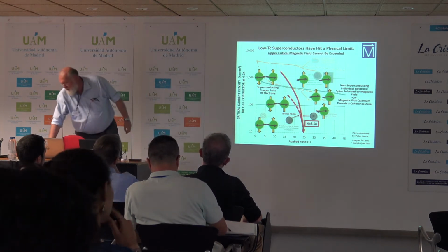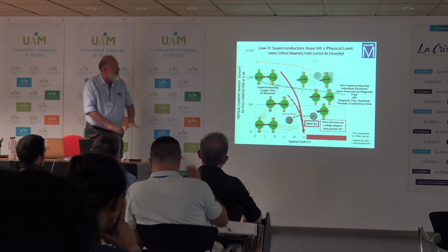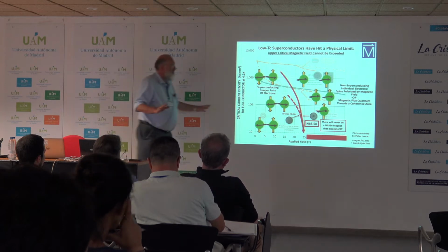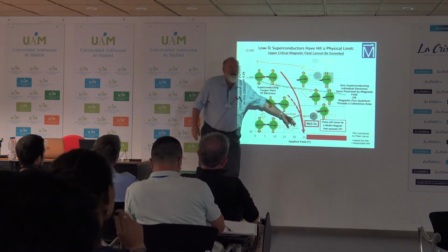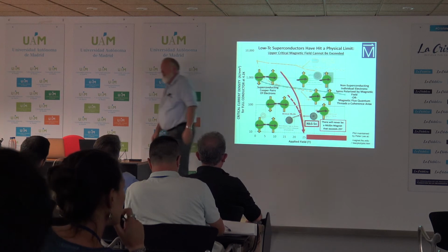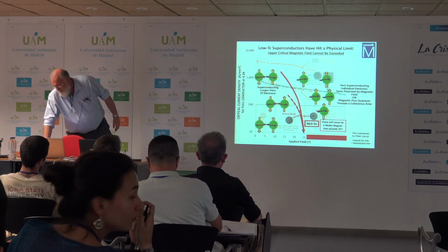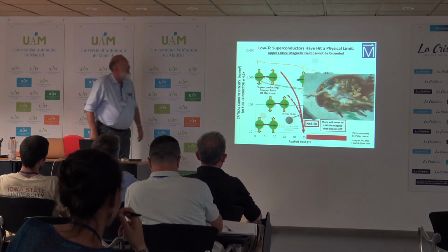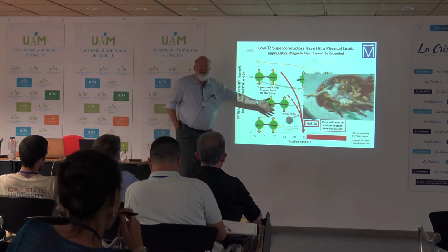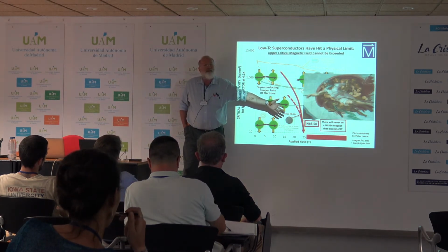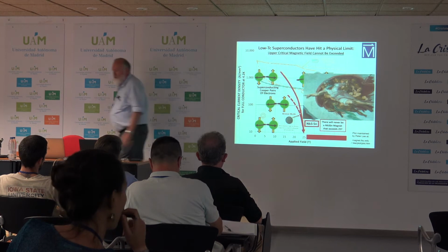And so for that reason, I make the assertion there will never be a niobium-3 tin magnet that exceeds 25 Tesla. And the reason is that this barrier is fundamental. It comes from on high, and it's given by the parameters of the superconductor itself. So how do low Tcs